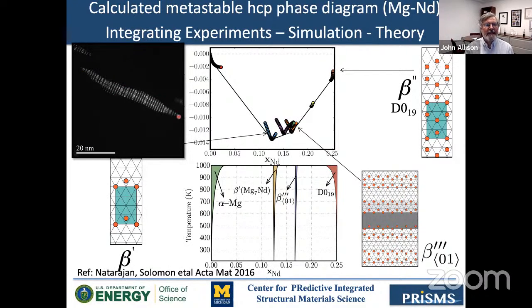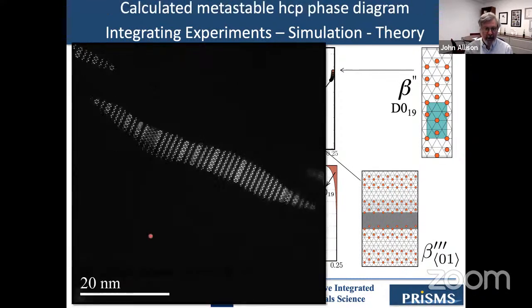Mg-neodymium has these sort of lenticular precipitates that are orthogonal to the basal plane and parallel to the prism plane. Prior to this, people were talking about beta prime, beta double prime, and DO19 type precipitates. But using CASM, we did some very detailed studies of these systems and actually came up with this new nomenclature called beta triple prime. And it was based on observations in high-res TEM of very repetitive structures within a given precipitate. So we have these rings that are like DO19, then these sort of checks and W's that really are indicative of local compositional fluctuations along this very tiny precipitate.